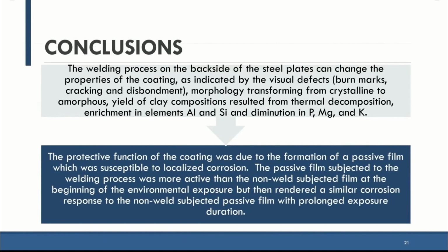One of the things you find out with this is that it fixes itself, so somebody would call it a self-healing system, different from what you think of as a polymeric self-healing system. But you would see the results of the data coalesce after a period of time and still give you corrosion protection. So it's evident here that even though we do see changes in chemistry from the heat of the weld, you still get a system which will give you corrosion protection. And that's the takeaway for us from the study.